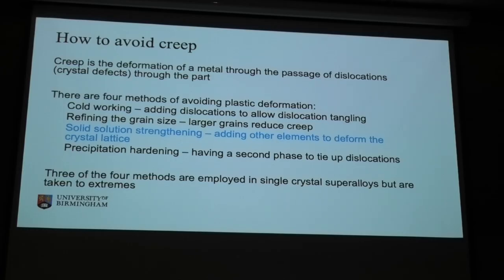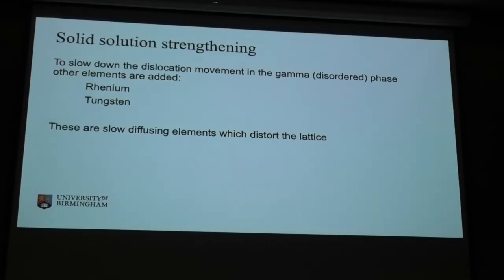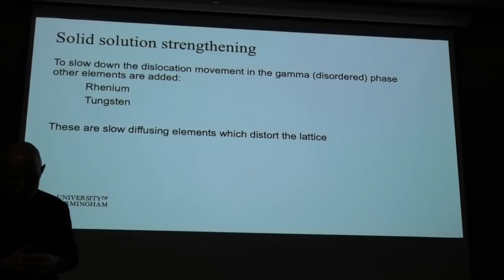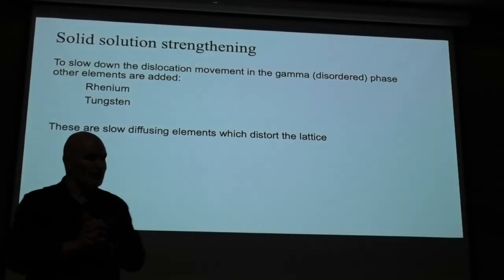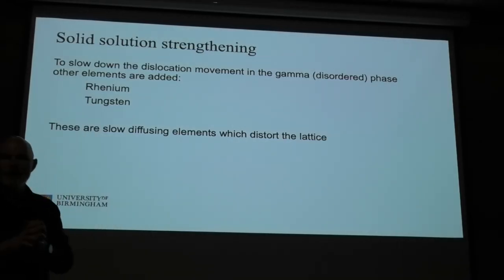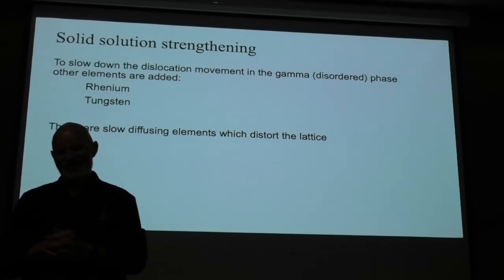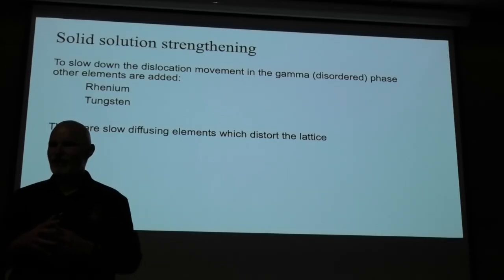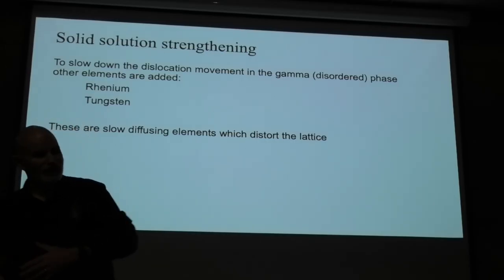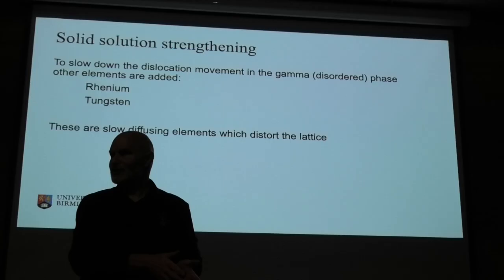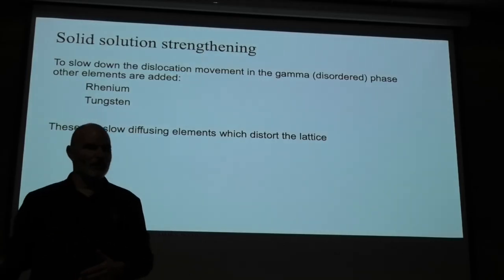We then add other elements to deform the crystal lattice to make sure we can work with what's left of the system. Because we've still got 30% of this disordered phase, not the precipitate, we shove in things like rhenium and tungsten. Great elements, they don't diffuse very fast, they get in the way, they just sit there like big blocking elements and tie up dislocations in the other phase. So if the dislocations try to get round the precipitate, they meet rhenium and tungsten. If they try to go through the precipitate, they've got to find a friend.